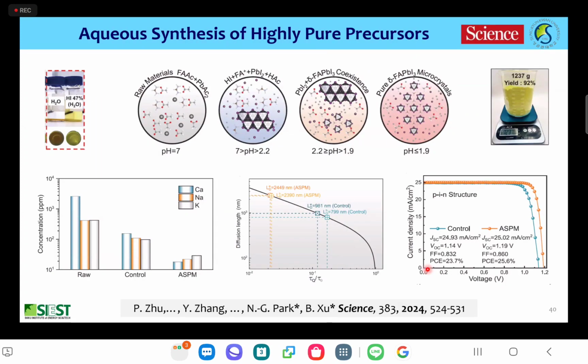One more thing that I would like to mention about the precursor material: we actually use PbI2 and FAI. In that case, those kinds of mixtures can induce some unwanted phase or impurity and so on. Therefore, we actually synthesized the perovskite delta phase as a precursor material using aqueous solution. In that case, the pH plays a very important role. We found that a pH less than 1.9 is quite a good condition for making pure delta phase FAPbI3. Using this pure FAPbI3, we can get over 25.6% efficiency. And also the electron and hole diffusion length is quite balanced as compared to the conventional PbI2 and FAI precursor mixture.